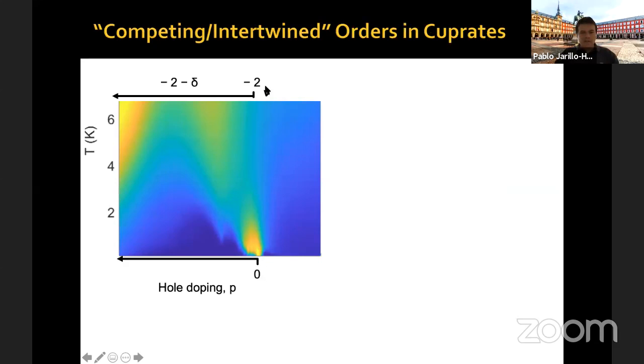Now let me zoom in a little bit more in this region. This is filling factor 2 holes per moiré unit cell. This is doping with extra holes, so -2 minus delta. In terms of just hole doping, this is 0 hole doping, and this is extra holes. So as you can see, there is this resistance maximum which is happening here, and it's about 10% off in terms of doping from this correlated insulator state. Now, as you can see, we have a superconducting dome which has a depletion here at this point.